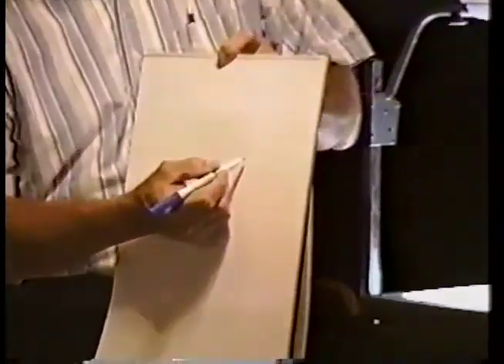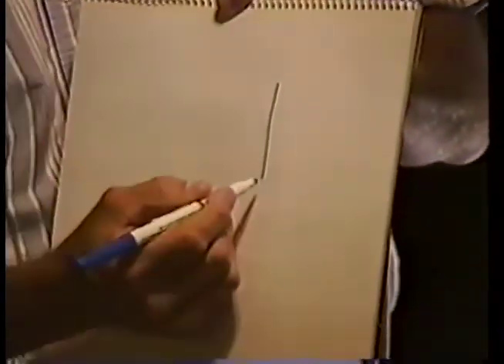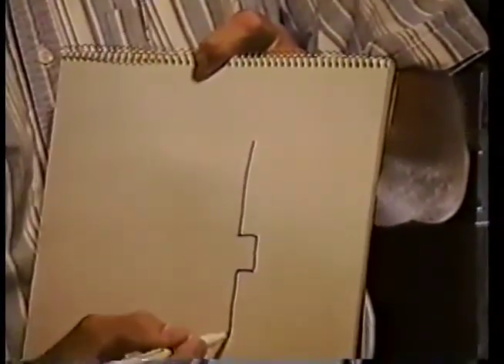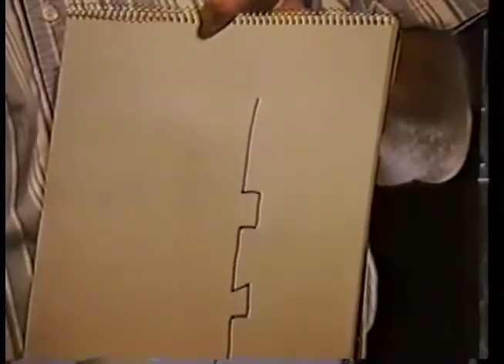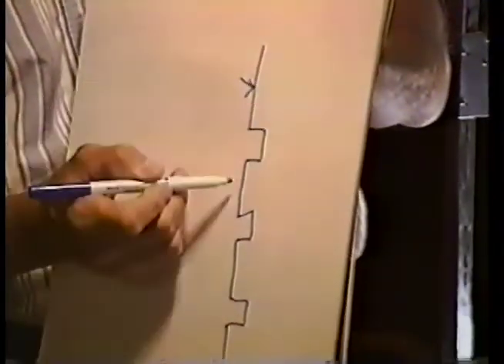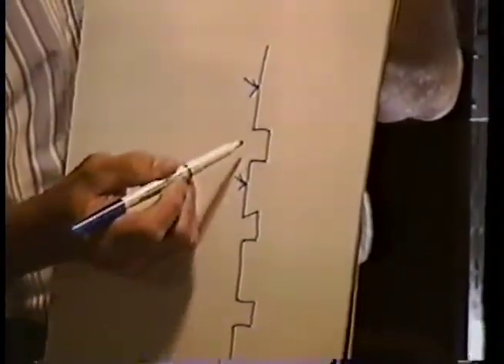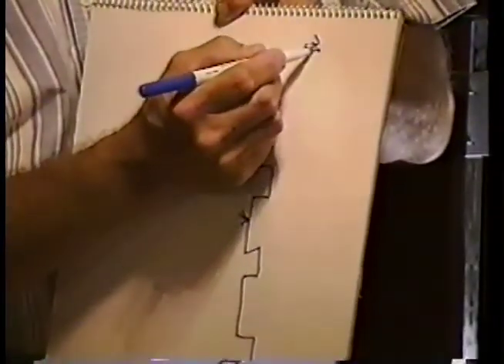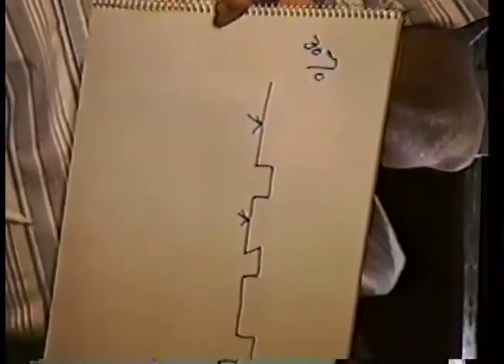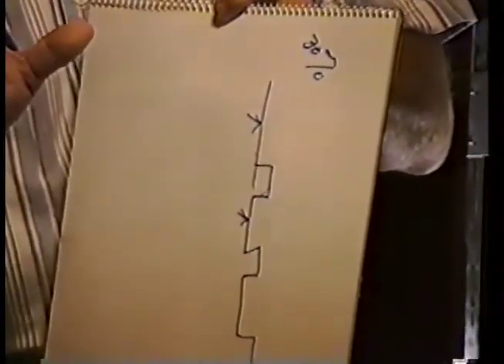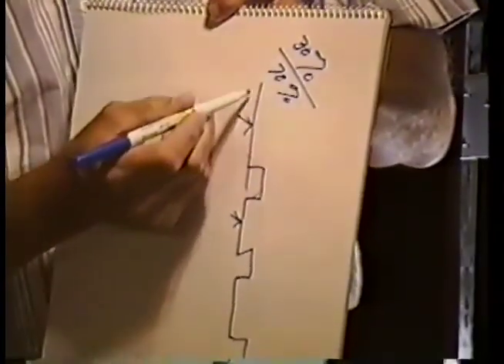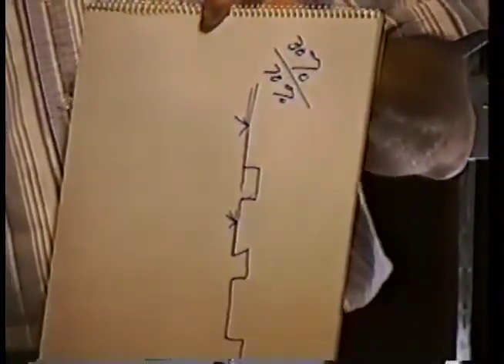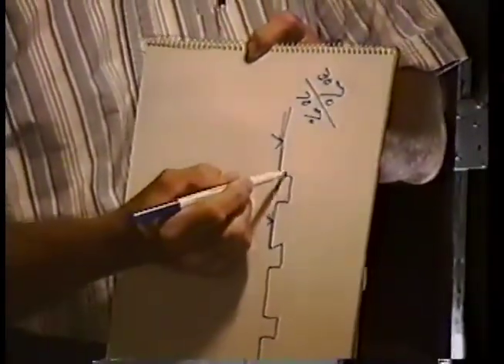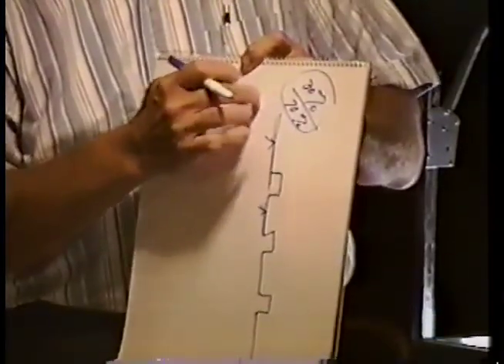One of the things that we try to do and must do to provide a good running surface is to give you as close a relationship as possible between the percentage of porosity, the number of pores in that chrome surface, and flat ring-bearing surface. In other words, ideally, if we have, say, 30% porosity, in other words, 30% of any one square inch has a hole in it that will retain lube, you should have as close to a 70% flat surface to carry the rings, to support the rings as they travel through the bore. That's the ideal situation. As close as you can get to that, the better you are.